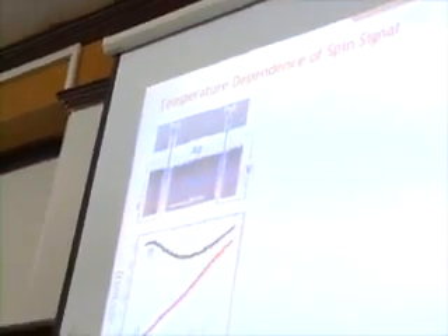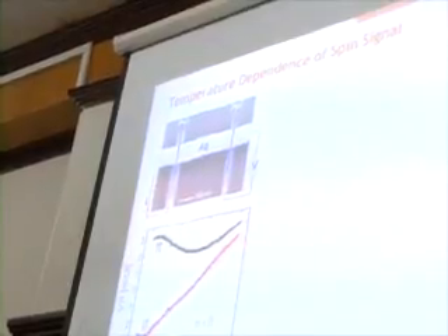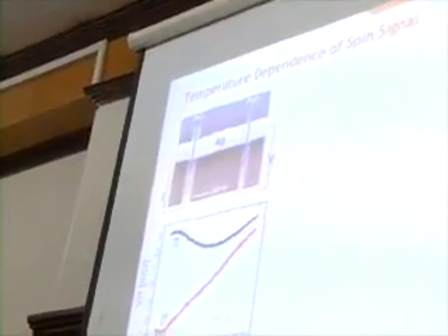And so we get a temperature gradient where this end is hotter than this end. And at some point we also get a temperature gradient here where the silver here is hotter than there. But this is nothing else but a thermocouple. You have two different metals in contact with each other. And so by having a temperature gradient, you get an electric voltage, a thermoelectric voltage. And this thermoelectric voltage then gives